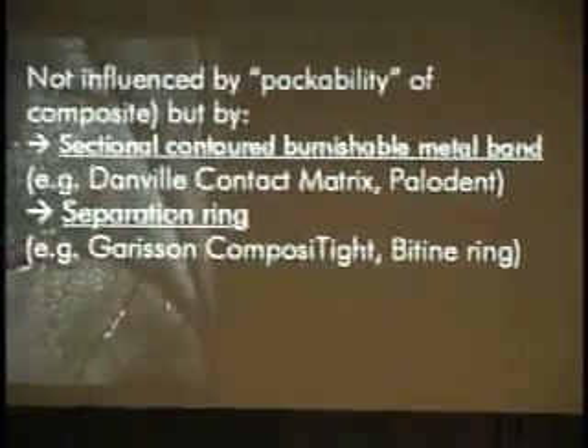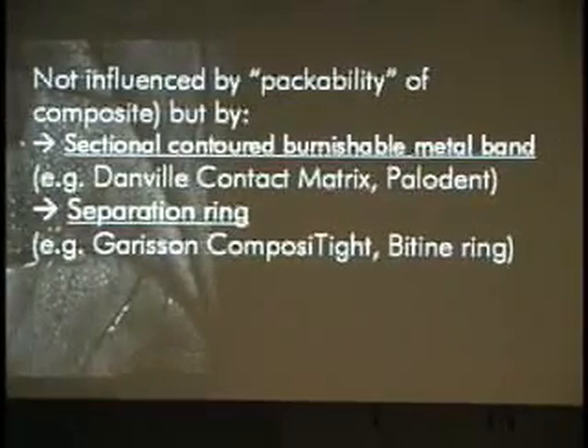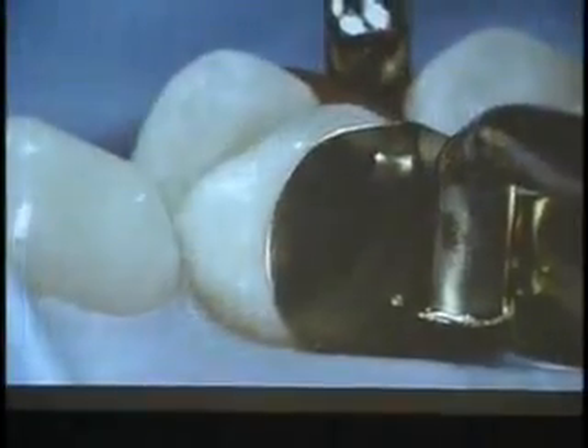In the management of the proximal area, another very common problem that was reported with composite at the beginning was the development of contact points, because with composite we don't pack them, we don't condense them, and for this reason it's much more difficult to get the contact point compared to amalgam restorations. And we know that with composite, whatever the stiffness, the packability of the composite doesn't change anything, because it's still too soft to be condensed. What is really going to make a difference are some innovative tools like sectioned, contoured, burnishable metal bands and separation rings. This is one example of a study that proved these tools allow us to compensate for the problem we had due to the floppiness of the composite when it's still uncured.